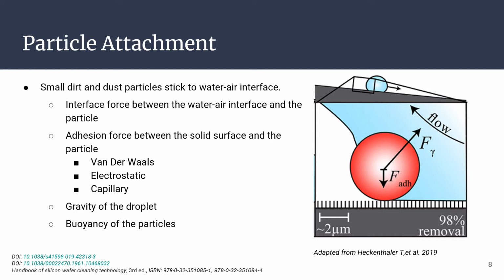These particles stick to the surfaces by different forces of adhesion. The van der Waals force is the most common force. It is a force between any two molecules or atoms which attracts them to each other. In areas of high humidity, small amounts of water vapor can condense around a particle, and the capillary forces hold the particle to the surface.